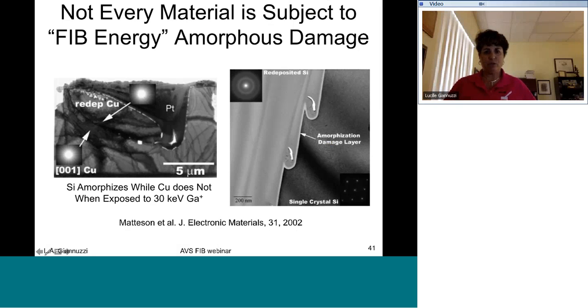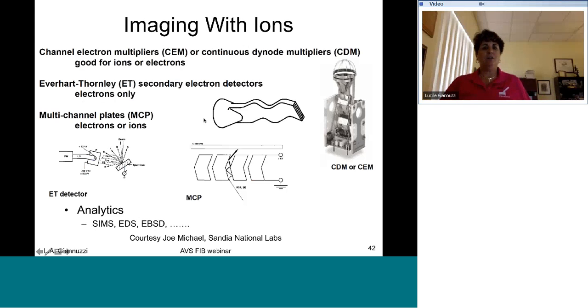So again, not everything forms an amorphous layer, and this on the left is copper, and on the right is silicon. And this is looking at a cross-section of a particular pattern. And there's evidence here for the redeposited material growing epitaxially on the copper, showing that there is no amorphous phase here as a result of the ion beam hitting the copper, whereas this, again, light layer in between this very dark silicon layer and the intermediate redeposited layer, which has a lot of gallium in it, shows that there is amorphization there.